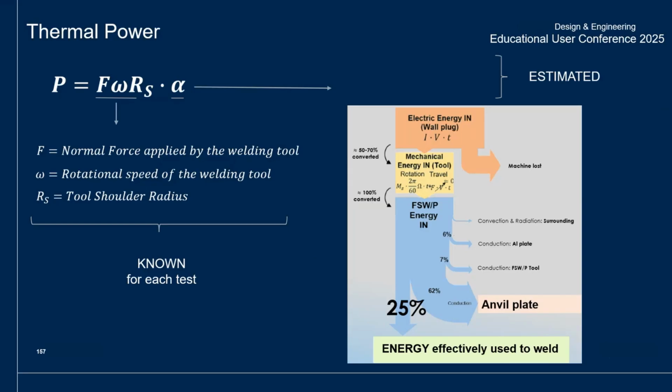The parameter that I indicate with the letter alpha instead has been introduced by me, and it takes into account 2 aspects of the process that cannot be measured experimentally, and are the friction coefficient between the tool and the welded material, and the dissipation, which the scientific literature demonstrates to be particularly high for the friction stir welding process. This parameter has been estimated for the Thales Alenia Space Italia welding machine through the simulation I'm currently presenting and is set equal to 0.163.